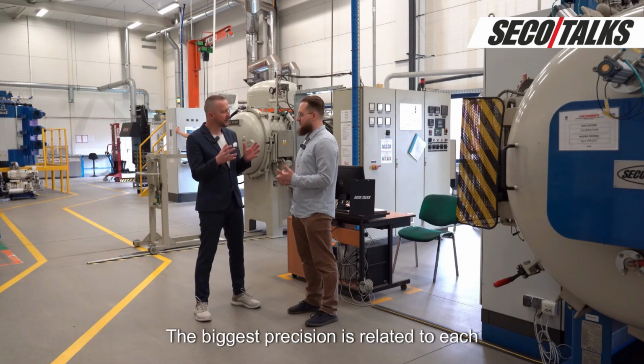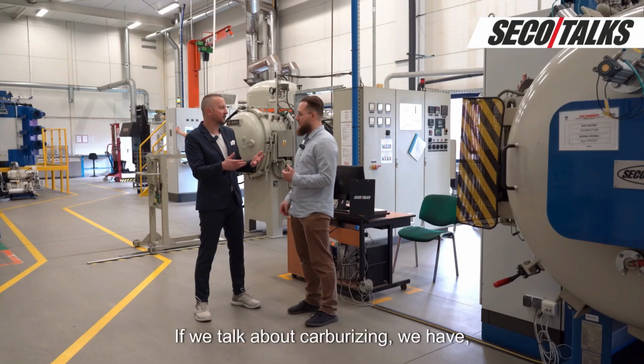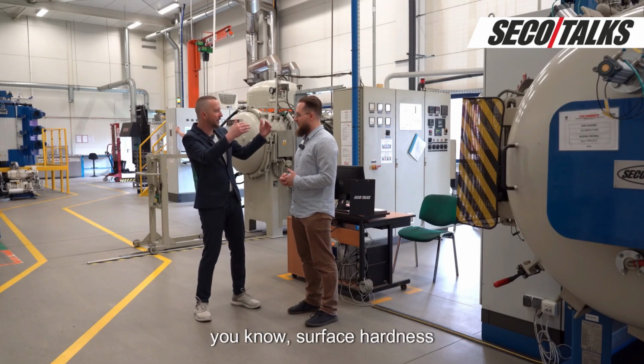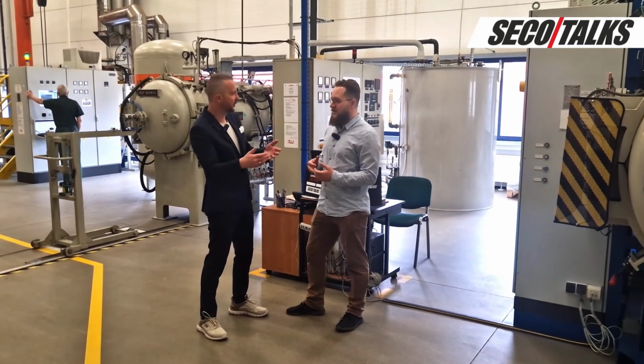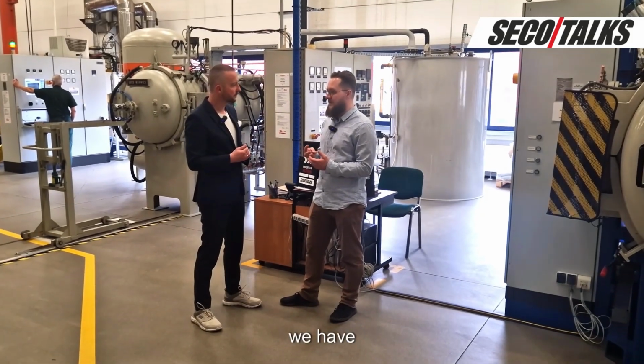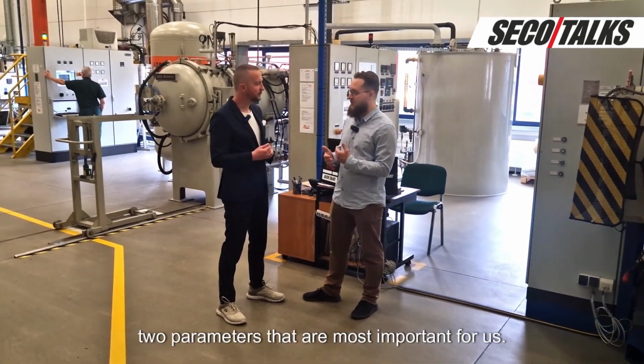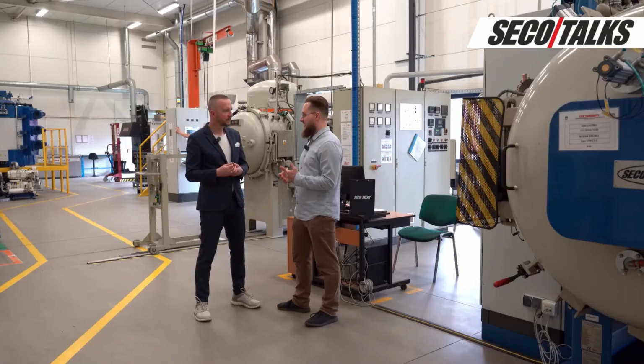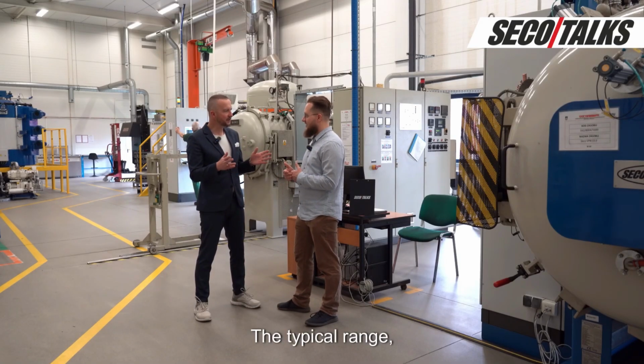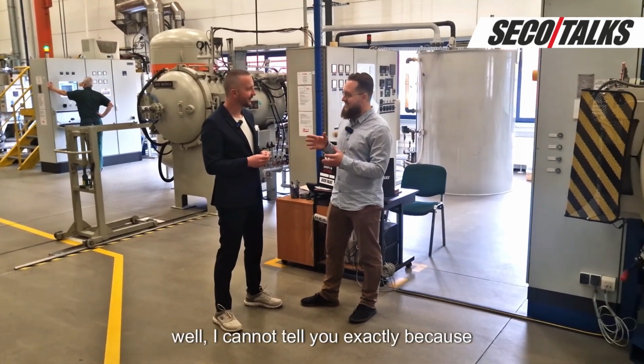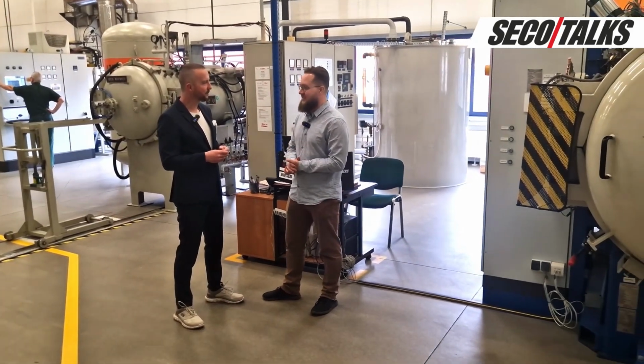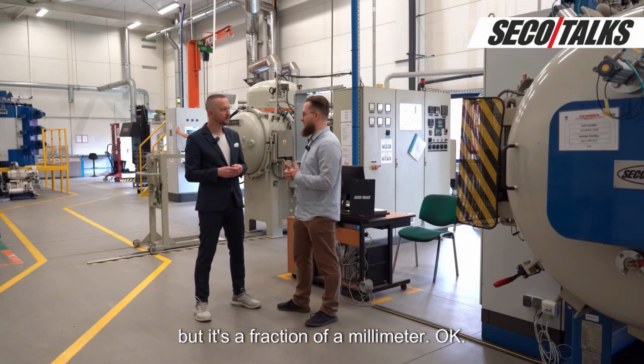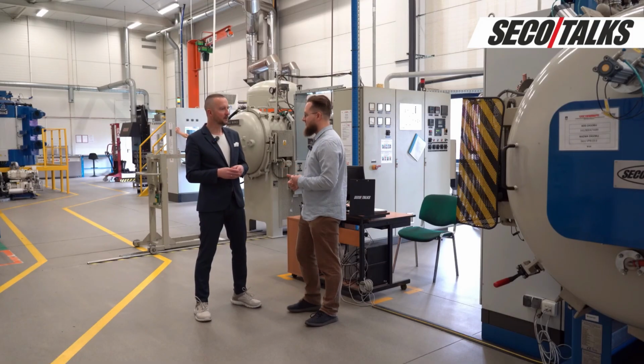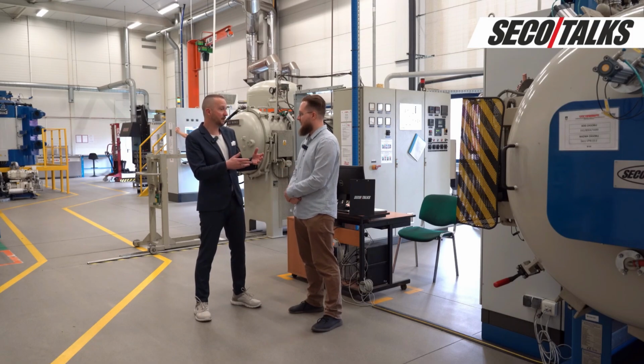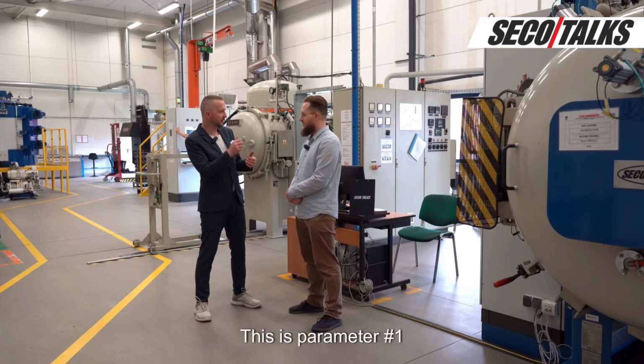So the biggest precision is related to which parameter? If we talk about carburizing, we have surface hardness, effective case depth. In this case, we have two parameters that are most important for us. The effective case depth of carburized material. What's the typical range? Well, I cannot tell you exactly, but it's a fraction of a millimeter. Okay, good. So you very much focus on the effective case depth. This is parameter number one.